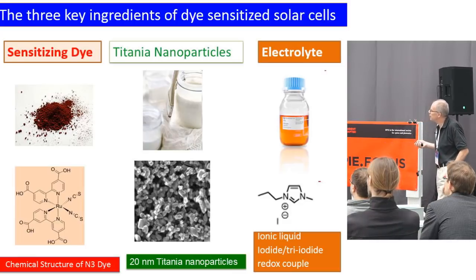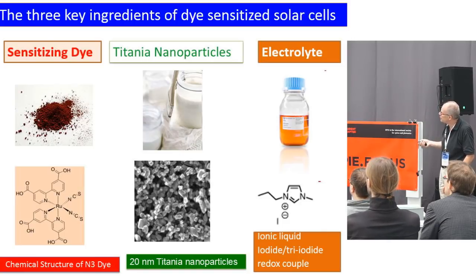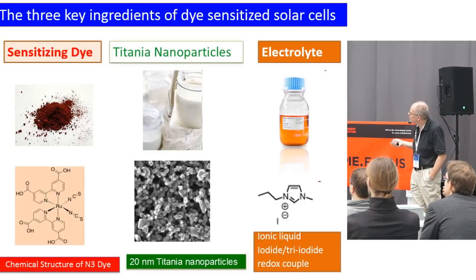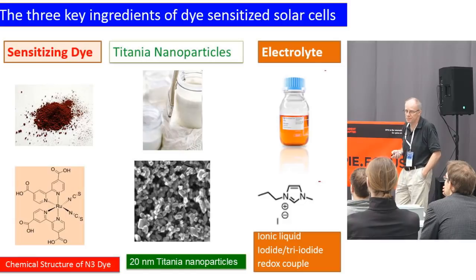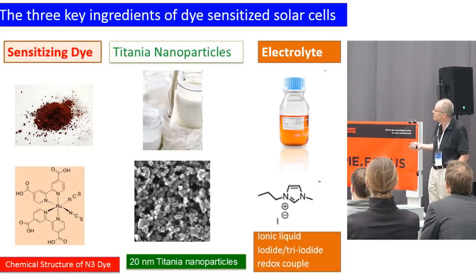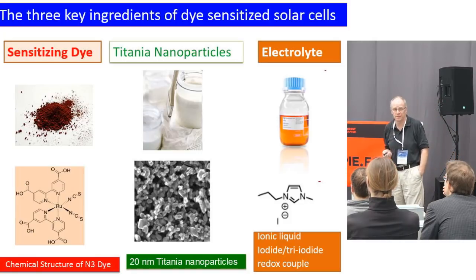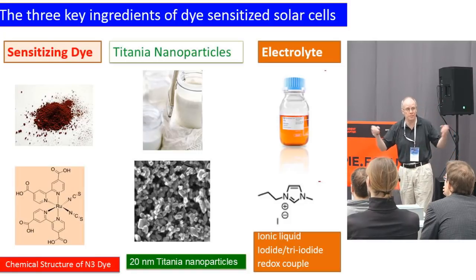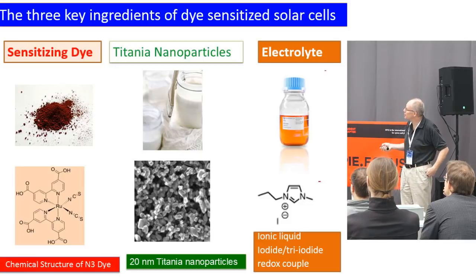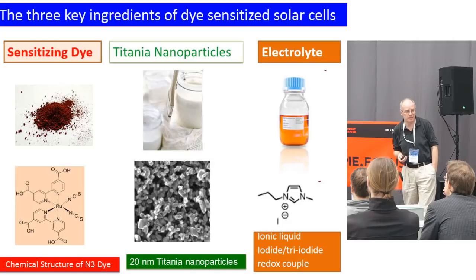The typical electrolyte was based on iodide and iodine. So this is a cation and the iodide salt, and that's your redox couple. And this was the best redox couple for about 20 years. So very difficult to change. This TiO2 is, after almost 30 years now, still the best. You can imagine hundreds of publications with nanorods, nanofibers, zinc oxide, tin oxide, niobium oxide, all kinds of oxide you can imagine. And nothing has come up better than the original thing.